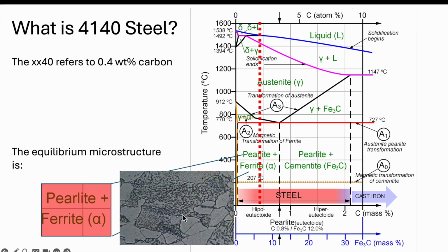Here's a quick picture of what this microstructure could look like. In the center, you'll see a layered structure with dark and light regions. The dark represents cementite, the carbide phase, and the lighter phase here and in the mixture as well is ferrite. The striped constituent is referred to as pearlite. Whenever you see that striped appearance, that's pearlite. And the uniform phase is ferrite. So we would expect 4140 steel, having a more equilibrium microstructure, to be pearlite and ferrite.